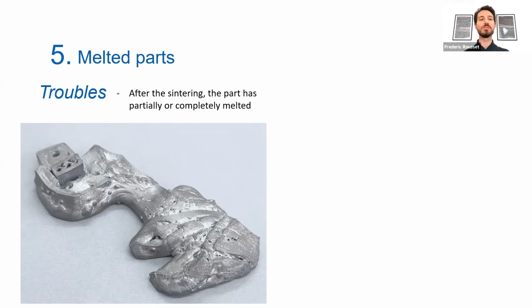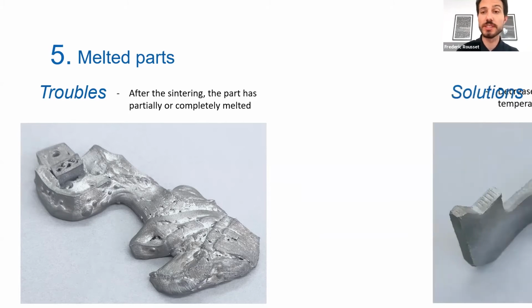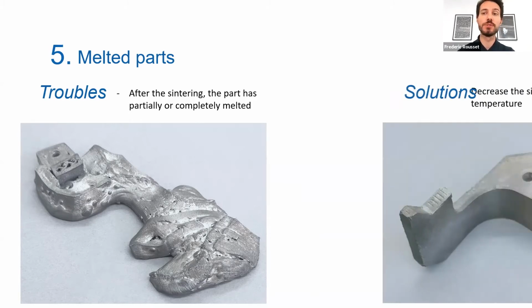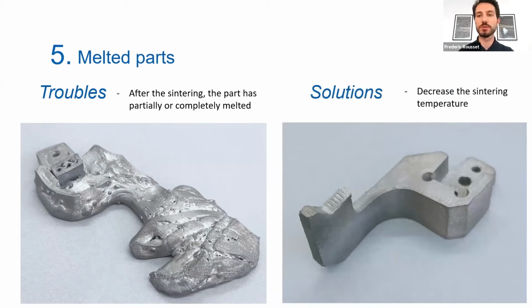So yeah, I was just talking about the melted parts that we have. This is quite rare. We had this only one time. The solution is quite simple. You have to decrease the sintering temperature. We have a guideline for this. You should be at 1350 degrees for the sintering of your part. You shouldn't go over it. If you go over it, you can have some melted parts. Not as much as you see on the picture, of course, but it can happen, so try to follow the guidelines if you can.